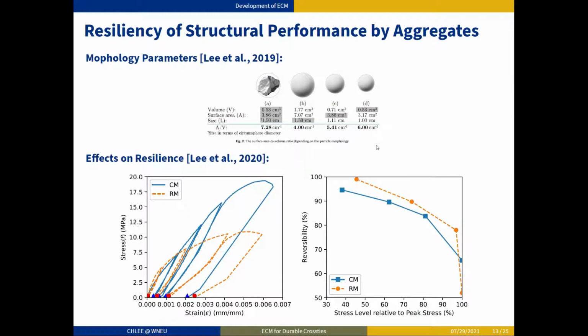When we became interested in the surface area of aggregates, we realized that the surface area is significantly influenced by the angularity of the particles. Please take a look at particle A as compared to particle D. They have the same volume of 0.53 cubic centimeters. However, their surface areas are significantly different from each other because of the shapes. As a result, the ratio between surface area and volume is significantly different. If you translate it to the mixture design, then you will need more paste content when you use angular aggregates. Then you will have less paste layer thickness if you use angular aggregates to achieve the same workability.